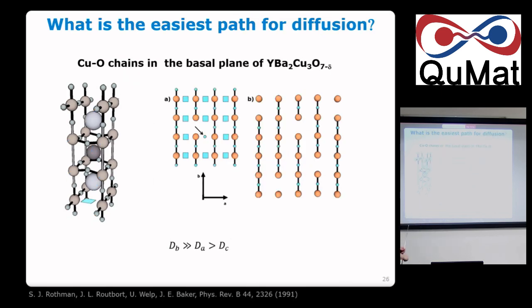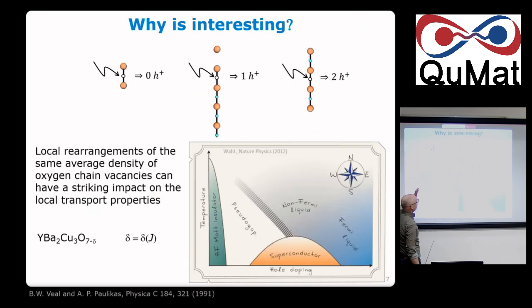So the idea is to apply current and try to move this. Once we put it here, the oxygen can diffuse very easily because there are empty places. Tick, tick, tick, tick, tick. Why is that interesting? Because there is a big fight on this system to understand the phase boundary. Basically temperature and hole doping: how many holes you have on the plane depends on how many oxygens you have on the chains. So if you move the oxygens, you can sweep this axis. I'm trying to go fast here because of time.